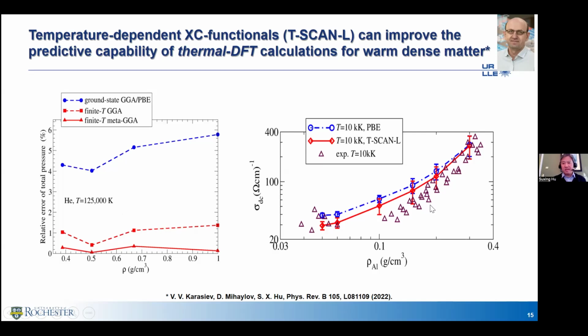For the right panel, I'll show you this: it's a conductivity calculation when you use this temperature-dependent one, aluminum at a 10,000 Kelvin temperature. It's moving towards the right direction. You get a better agreement with the experiment.